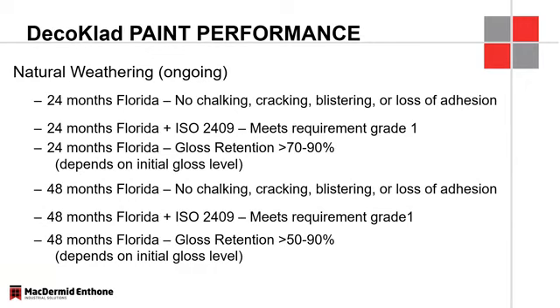Natural weathering, so Florida weathering, and we're still in the process of doing that because it is such a long cycle, 48 months, so 4 years in Florida weathering, and still not showing any signs of cracking or blistering, no adhesion loss, tape test, gloss retention. These are all things that are continuing to be monitored as these finishes are gaining approval.